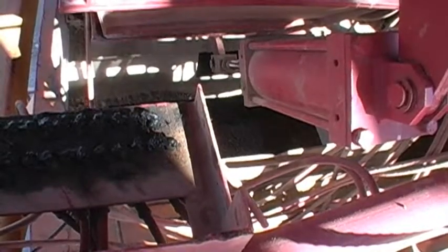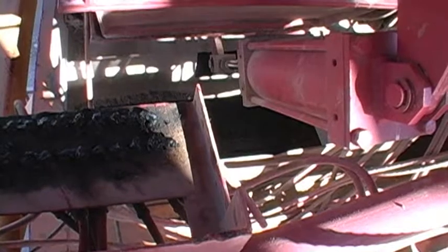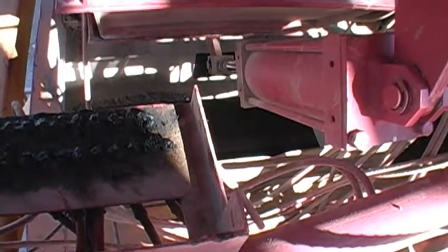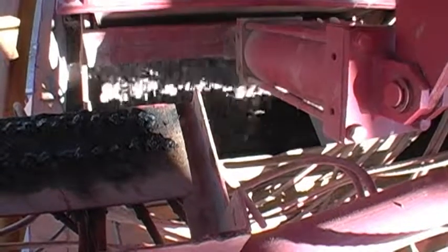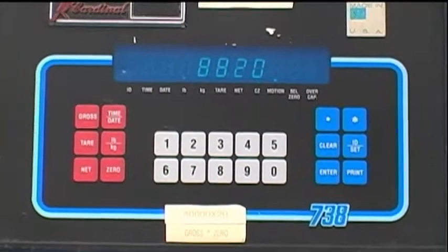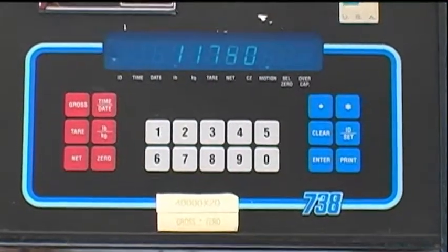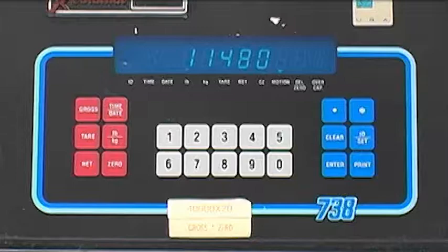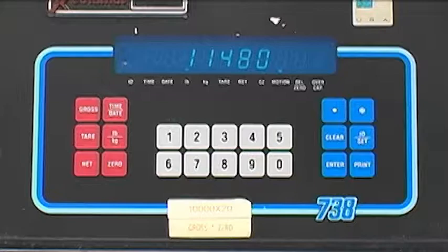Here the rock is being weighed first. We have an intended batch weight for the rock of 11,450. The rock gate opens, allowing the rock to drop into the scales. When it gets to its target weight, it will close. The scales should read 11,450. However, with a 1% delivery tolerance, or 114 pounds, we need to be in the range of 11,336 to 11,564. In this case, we are in tolerance.